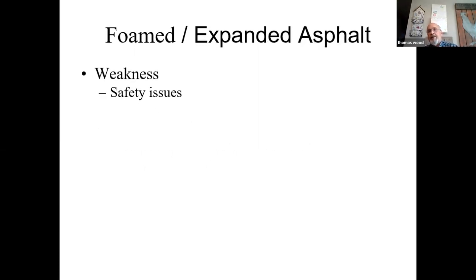Weaknesses. The biggest issue I have had with foamed asphalt is that in order to foam it, you have to have the asphalt binder hot enough that when you inject water into it, it turns to foam. And the idea is, if you just sprayed straight hot liquid asphalt into your recycling pug mill, or into the reclaimer, or this cold central plant, it would ball up because the aggregate and the millings are all cool and they can be damp. And so it wouldn't uniformly disperse.